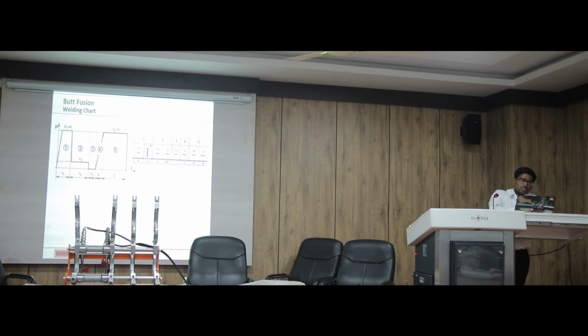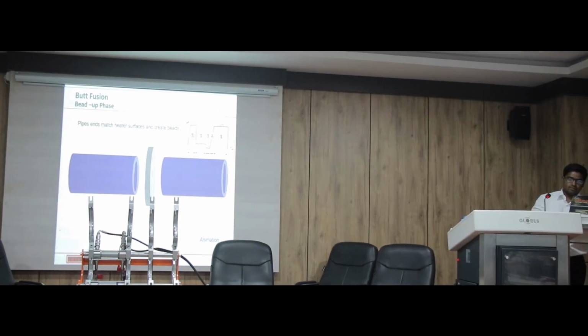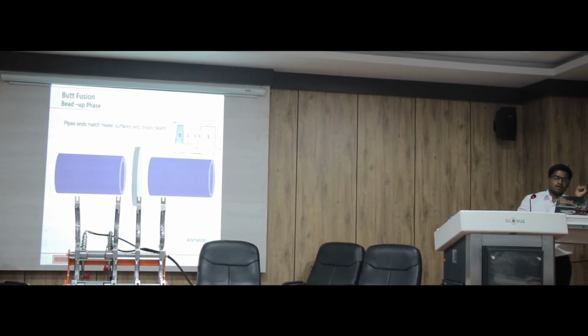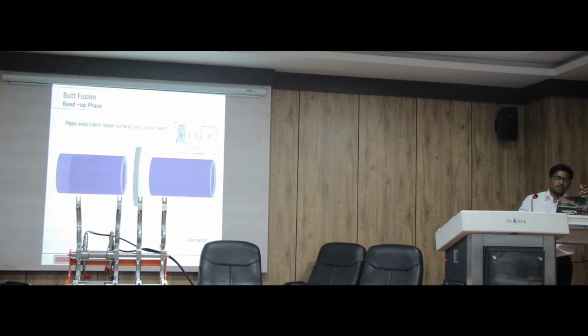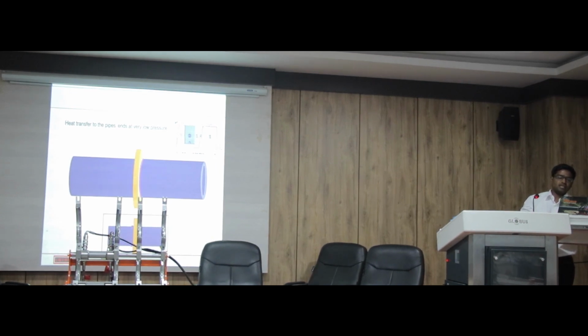So the second phase, during the heating, once we achieve the desired bead thickness of 2.5 mm as mentioned in column 1, we will drop the pressure to a value equal to or less than drag pressure. We are going to do that. Then we will maintain it up to time T2. As I explained, in the first phase we are closing, and you may see a bead forms, and we reduce the pressure.